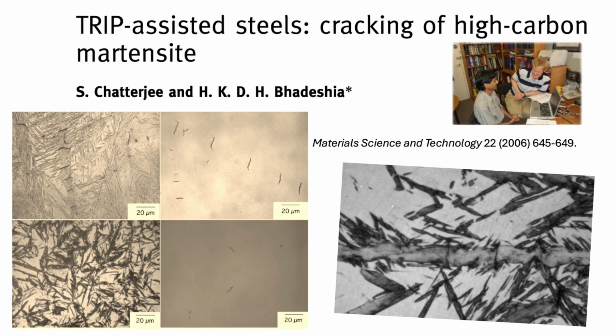Did the size matter? It mattered hugely. In the samples with the coarse grains, the ones treated at 1100 or 1200 C, they saw exactly what you'd expect. Large martensite plates and clear micro cracks within those plates. So the big plates were cracking. Yes, some of the longest plates looked like they were periodically cracked along their length, just like those brittle fibers we talked about failing under load.